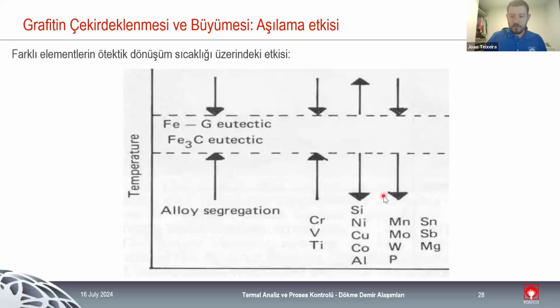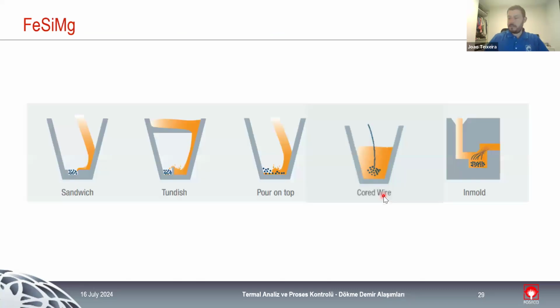This is just for us to understand that everything that we have in the base metal and everything that we had during production will have some effect during solidification. And the other treatment that we normally use for cast iron, in this case only for compact and for nodular, is the magnesium treatment. The main ones are the sandwich treatment, simply pour on top, core wire, which is really popular at the moment, and in-mold